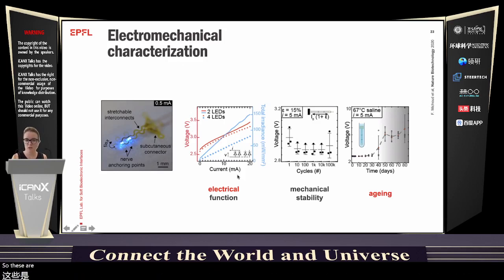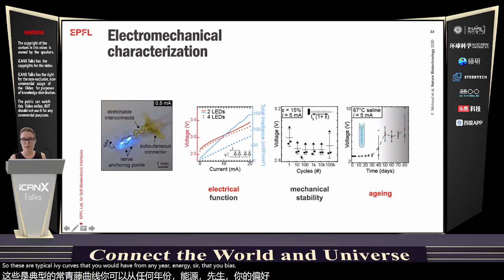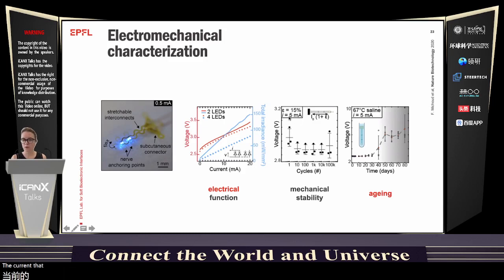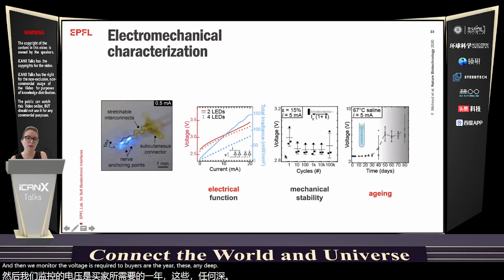So these are typical IV curves that you will have from any LED that you bias. Then the second step is to monitor the voltage while we bias the LED at a specific current, 5 milliamps in that context. But now we apply mechanical cycling of our device to a specific value, in this case 15%. And then we monitor the voltage that is required to bias this LED, the resulting voltage that can be measured across the LED as a function of the cyclic fatigue.